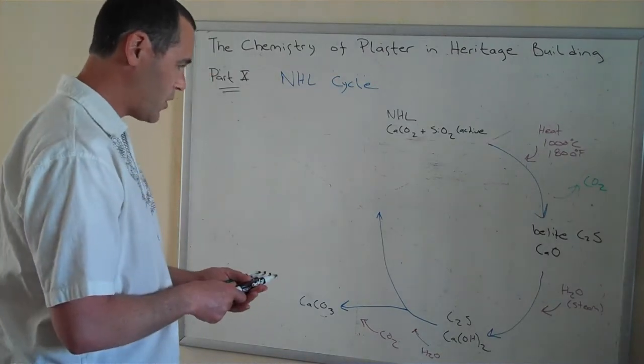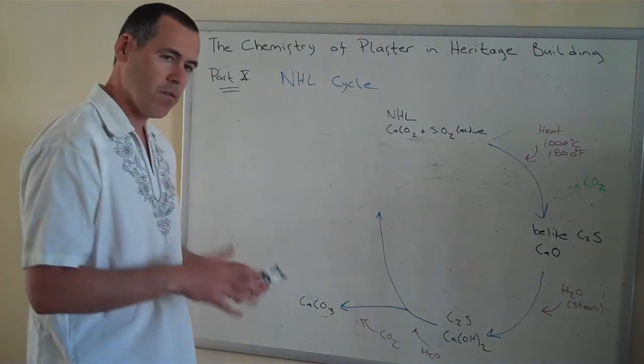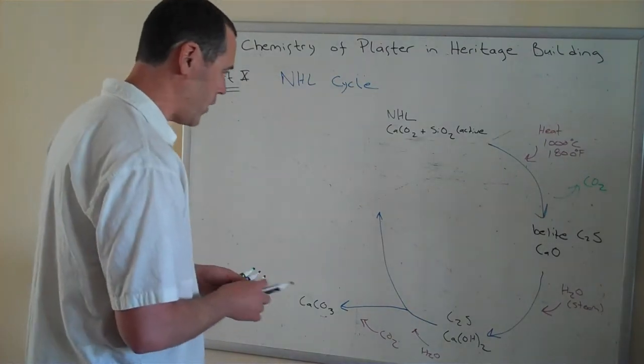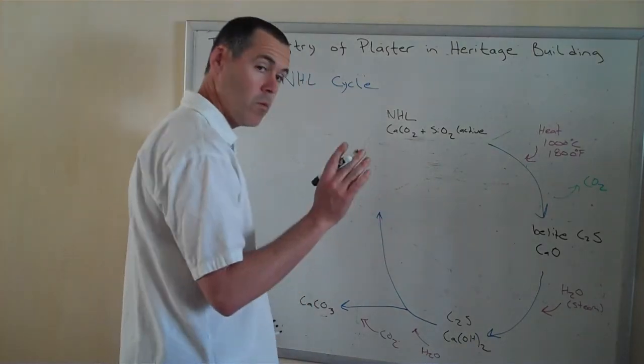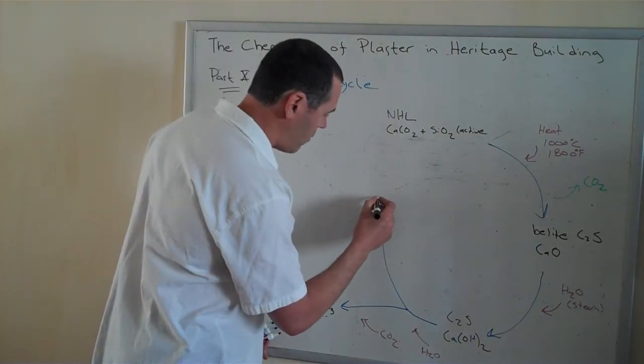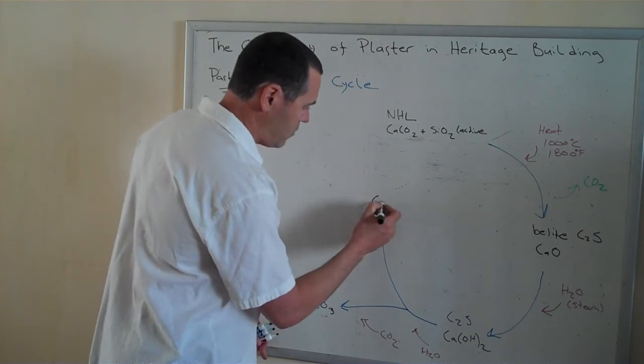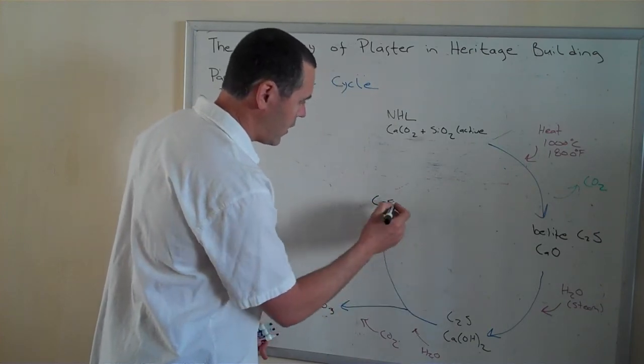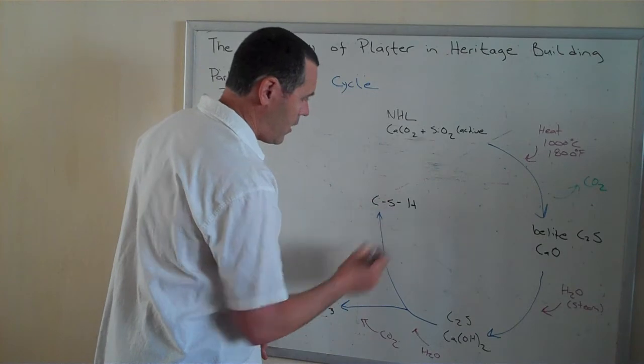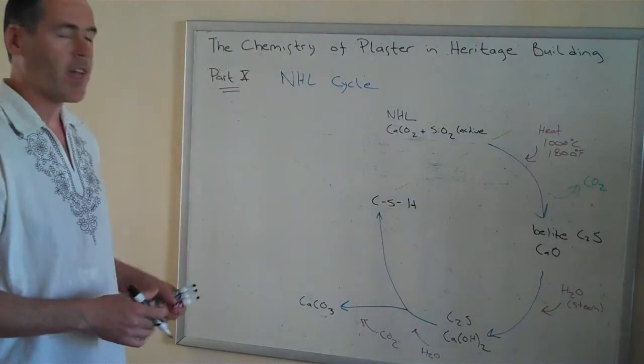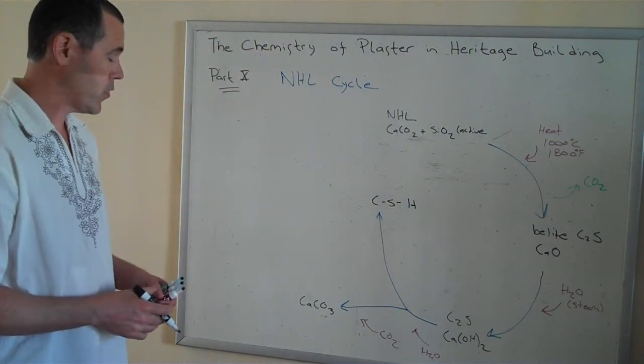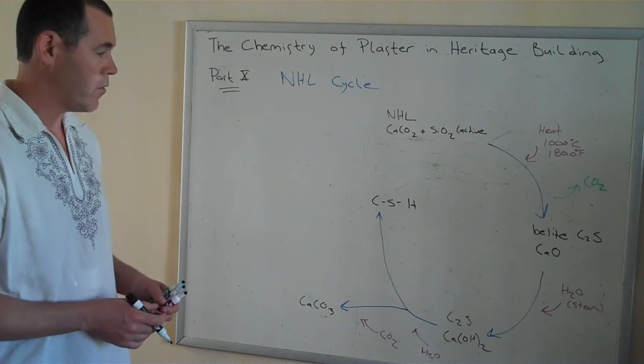But a percentage of our lime, it's going to vary depending on how hydraulic it is, is going to form more quickly by reacting with dicalcium silicate and the water to form these hydrous calcium silicate materials, and there are actually a variety of them.